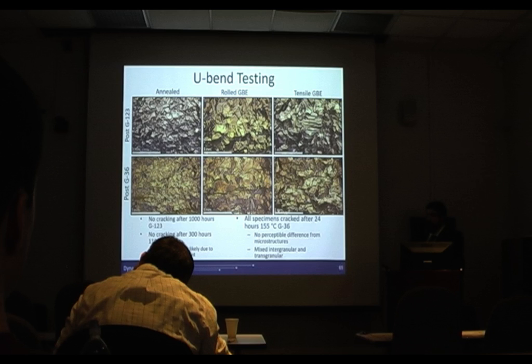The rolled GB microstructure appears more corrosion resistant than the conventional one. It's got larger length fraction in every criteria. It's got less deviation from ideal sigma 3, more of the sigma 3 junctions, similar grain size, and similar sigma 3 color microstructures. The A262 practice B shows that tensile GB has lower mass loss in every condition except for that 1,000-hour sensitization, where we saw the change in the surface texture as well.